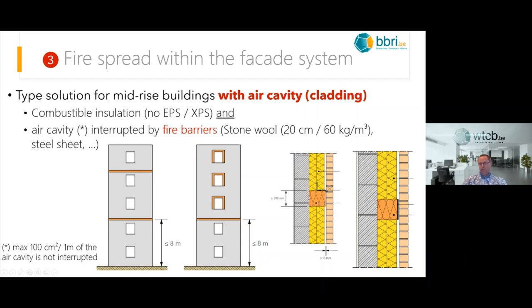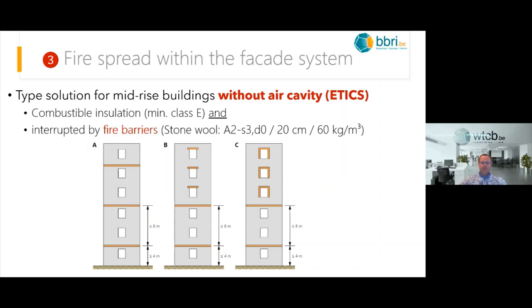The fire barrier will mostly be stone wool with a minimum height of 20 centimeters, but you can also use stone wool with an intumescent layer, so the cavity will be sealed in case of fire. That is also permitted by the Belgian legislation. The type solutions for facade systems without an air cavity, so the ETICS systems: there the insulation can be combustible, so a minimum class E, but there must be an interruption by fire barriers, always stone wool, every two floors or around the opening of the windows.